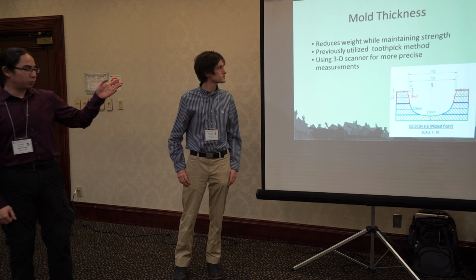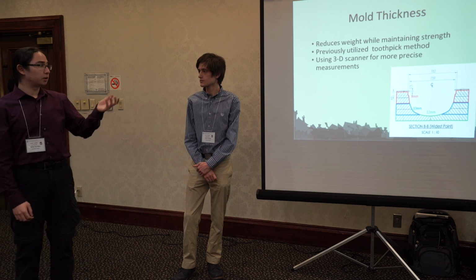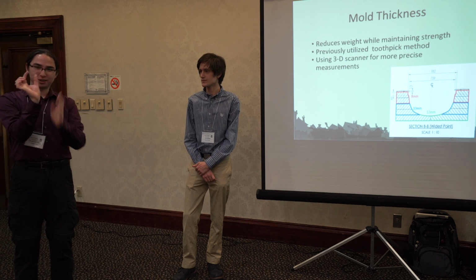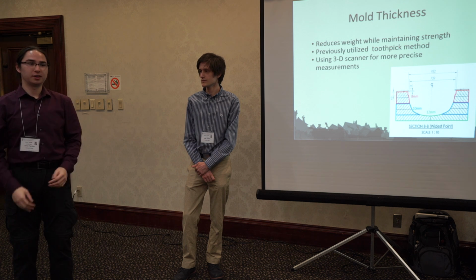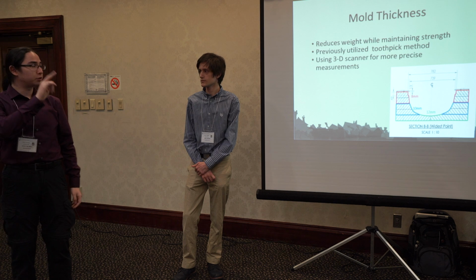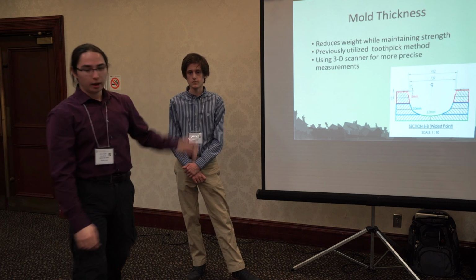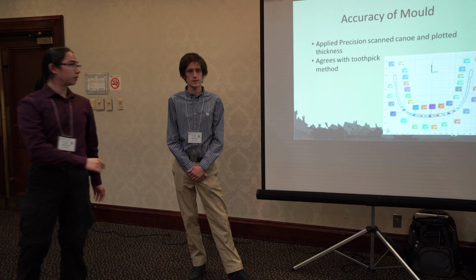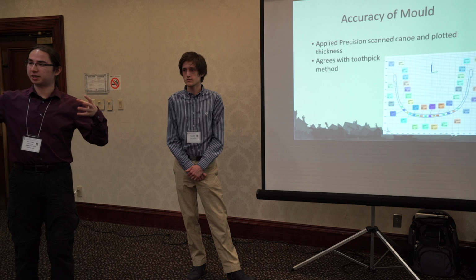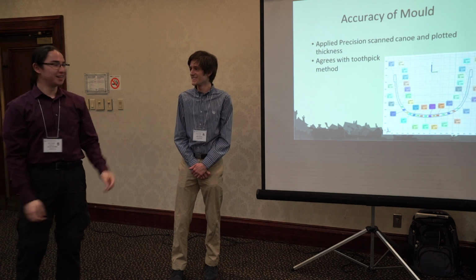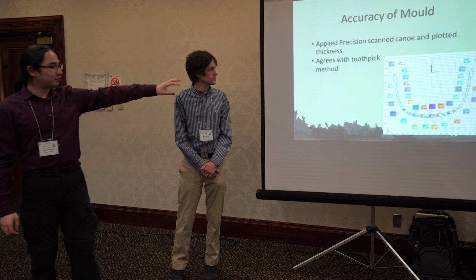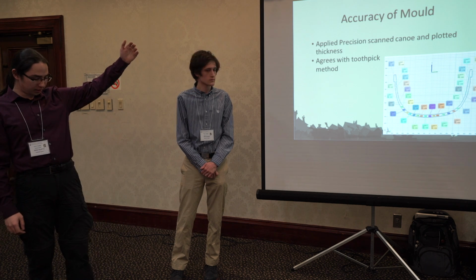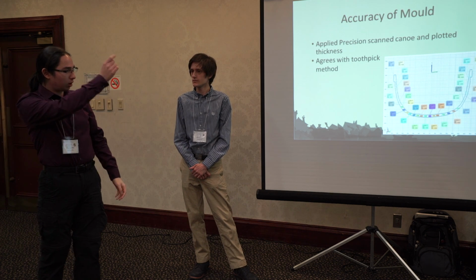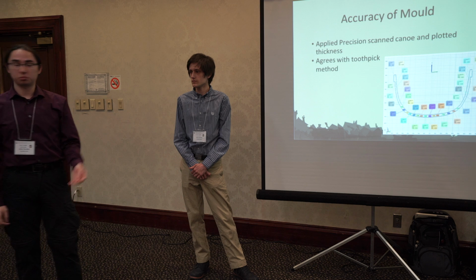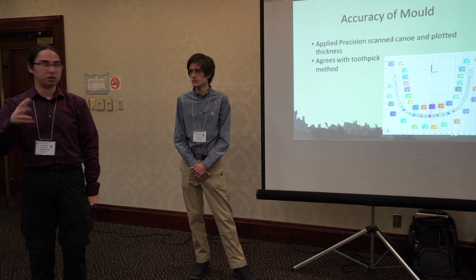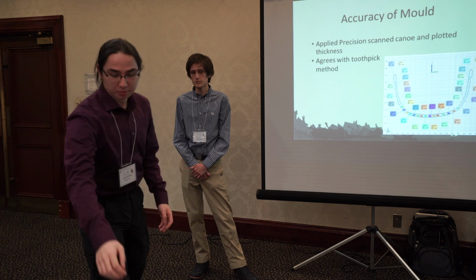We had a major problem with ensuring that the thickness was correct. So we took toothpicks, measured out the required thickness, marked it off, and then stuck them in the mold. Using that, we cast up to the marking on the toothpick to ensure the correct thickness. Then, to ensure the accuracy of our thickness, we got a massive 3D laser scanner and ran it along the cross section of the canoe to check the thickness. Here's the output of the scanner, which shows the cross-sectional distance along the entire canoe. We found that we were quite accurate, basically within 0.5 millimeters of what we wanted. So we were quite happy with how that turned out.